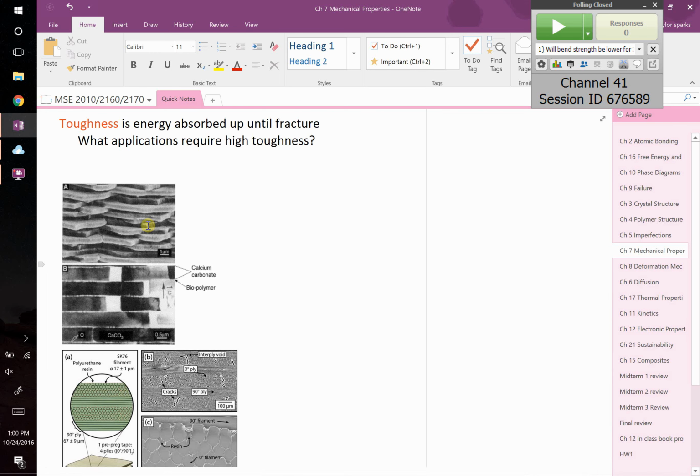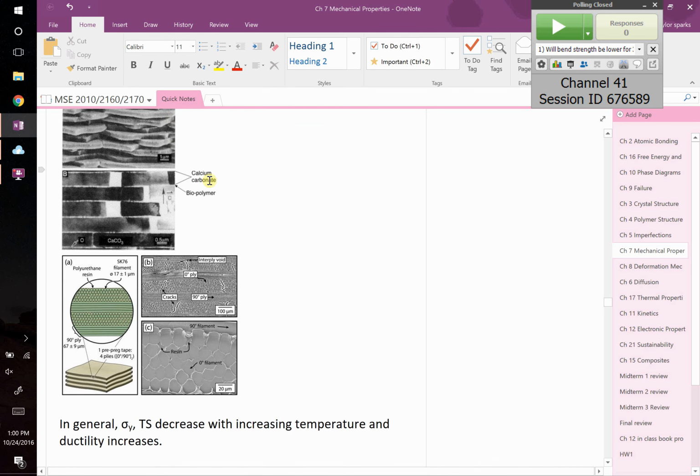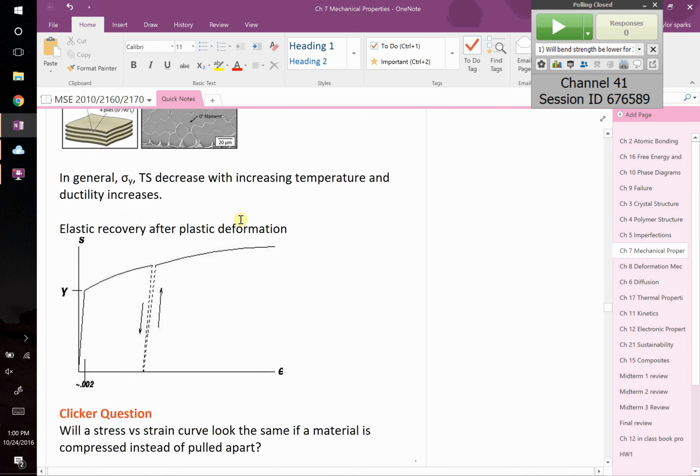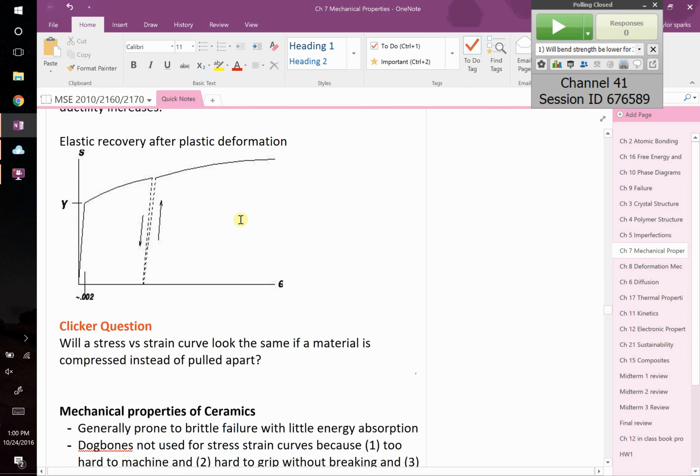You take a hard layer, like a ceramic, and then you put a polymer layer, something compliant, in between, and you do a lot of layers like that. That very simple layering is actually a great way to introduce toughness into materials. It gives you much more plastic deformation before the thing breaks, because individual sheets of hard things can break without the entire thing breaking. A lot of these will be calcium carbonate, a ceramic, followed by some biopolymer between them. And material science has taken a big page from that. They've invented a lot of things mirrored off of that.